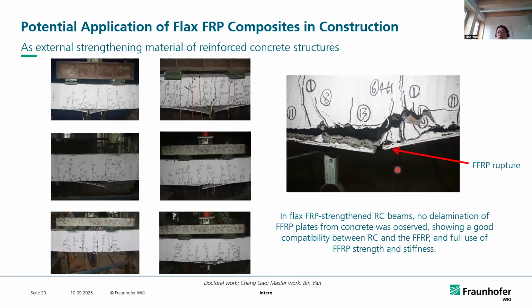It's quite interesting to point out that for the flax FRP reinforced RC beam, the typical failure is the rupture of the flax FRP, which means the full tensile strength of the composite can be used. But for the traditional glass or carbon FRP strengthened RC beam, we know debonding is always a critical issue.